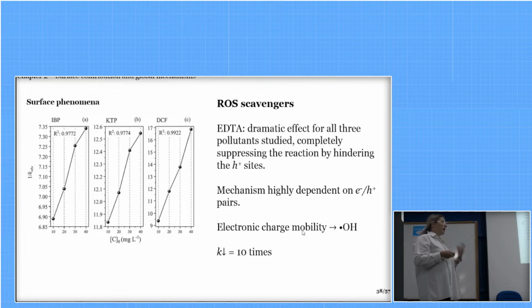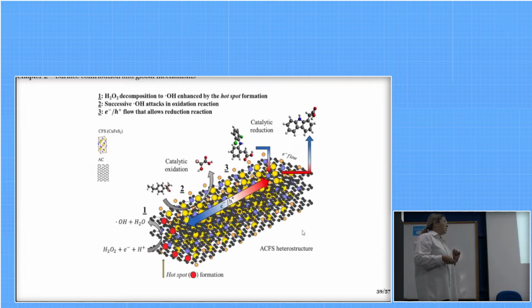And we saw that the mechanism was highly dependent on the formation of electron hole vacancies. And the electronic charge mobility by the formation of hydroxyl radical was also confirmed by the addition of isopropyl alcohol, which decreased the kinetic rate approximately 10 times. So we proposed a general mechanism for the catalytic degradation of these three substances on the surface of the ACFS heterostructure, where the decomposition of hydrogen peroxide formed hydroxyl radical enhanced by hotspot formation, so here the first possible mechanism occurring, then the catalytic oxidation by the attacks made by the hydroxyl radical, and the catalytic reduction due to the electronic flow on the surface of the material.